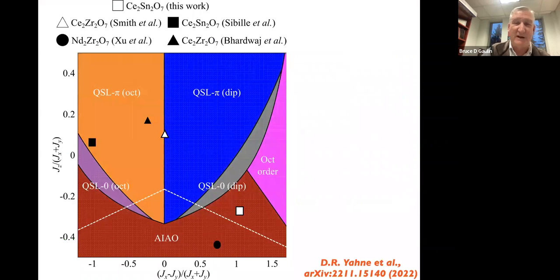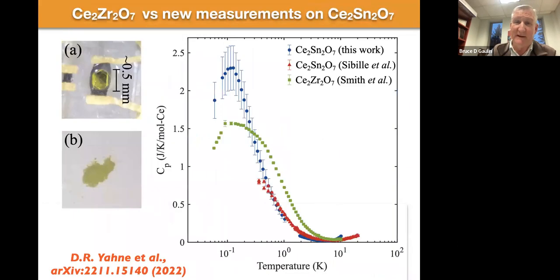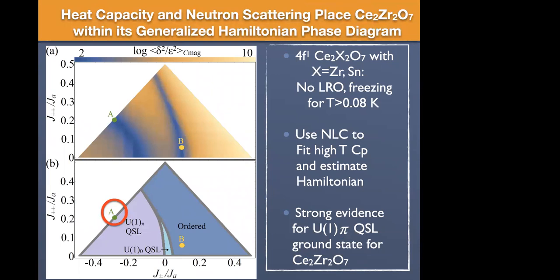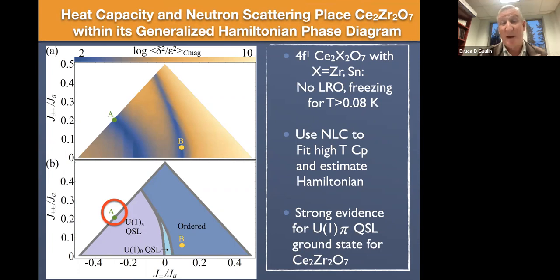So this is the first phase diagram that I showed you, and that boundary there is actually the open triangle here. And what it means is actually the fact that we have these two exchange constants that are almost the same magnitude, that are almost the same strength. It means that it's definitely a quantum disordered state, but it's right at the boundary between having the octupolar interactions dominate and the dipolar interactions dominate. But it's just the particular point here that it sits on. And so that point is this point here. They're the same point. Okay. All right. Thanks. So there's no special significance to being on the boundary, but it does mean that the strength of the octupolar interactions is similar to the strength of the dipolar interactions, if you like. Okay.